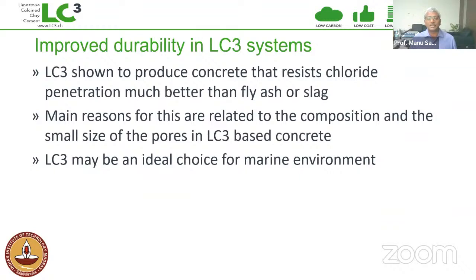Now, LC3 concretes, we've had years of research now. Overall, from IIT Delhi and Madras and Tara together, we've produced data in India for the last nearly 8 years. And with this data, we are quite confident that LC3 performs excellently in chloride environments, even better than fly ash and slag. The main reason is basically the composition of the hydrated products and the small size of the pores that we have in LC3-based concrete. So based on this, we have concluded that LC3 is an ideal choice for a marine environment where we expect a lot of chloride-related problems, especially corrosion.